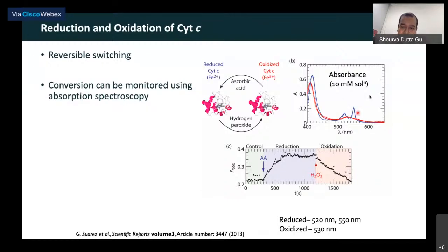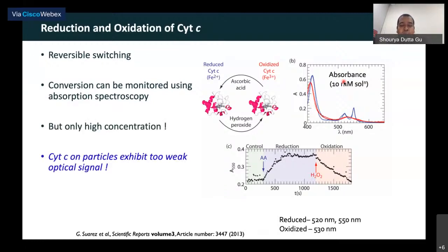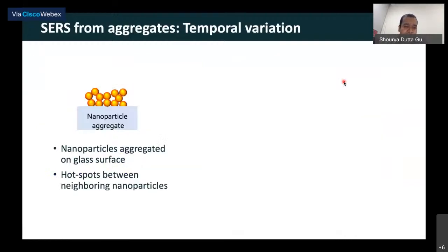However, if you notice, the concentration that I used here is 10 millimolar, which is very large, right? So now on a single particle, we have around 100 molecules. That would come in femtomolars or zeptomolars, right? A very small concentration. So UV visible absorption cannot work with single particle measurements. And in fact, if you take the synthesized particles and try to do UV-vis, you will not get a signal, right? So we have to enhance the signal somehow. And that is where plasmonics comes in.